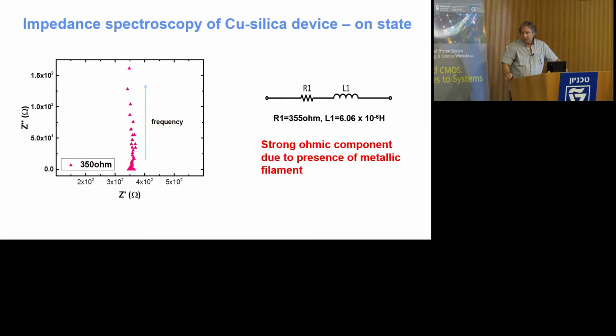Nick Onofrio out of Hong Kong has done some very nice work in modeling these intermediate on states in these copper silicon dioxide devices, and you can see these tenuous copper filaments being responsible for the higher resistance on states.